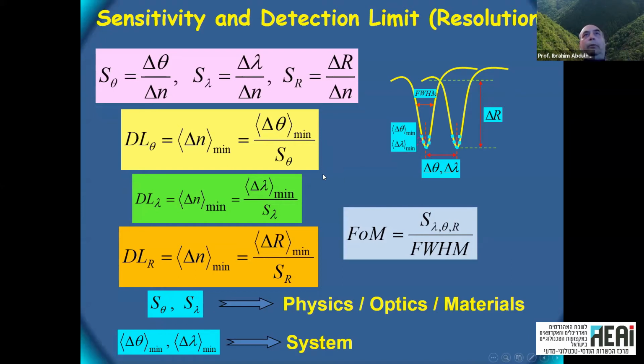Okay, you can argue, maybe make it twice, like having SNR equal 2 or 3 to get more reliable result. But more or less, it's determined by this relation, which means if I have larger sensitivity, I get better resolution. If I have a better system, I get better resolution. And also if I have narrower resonance, then the minimum delta theta I can measure will be better, and the same with the minimum delta lambda.